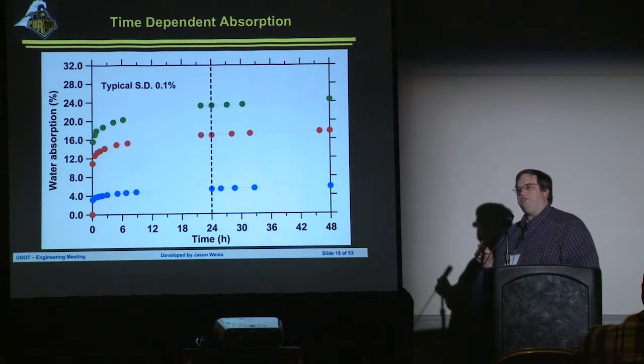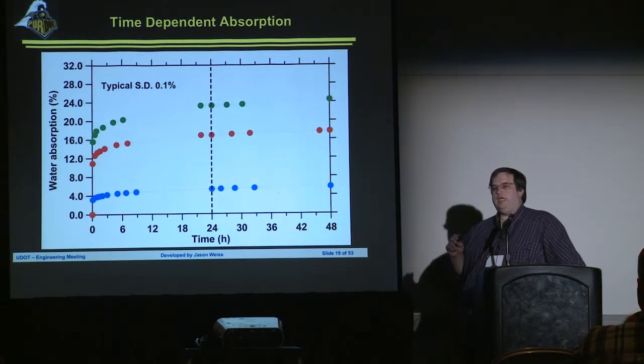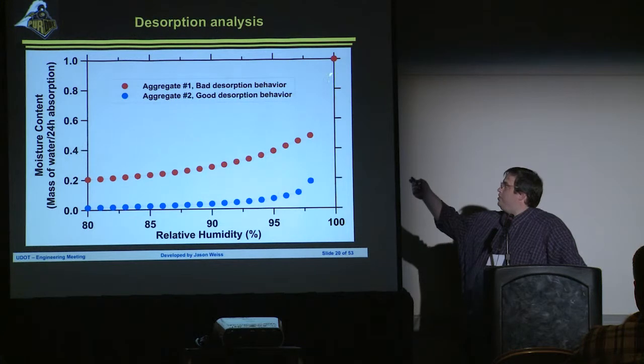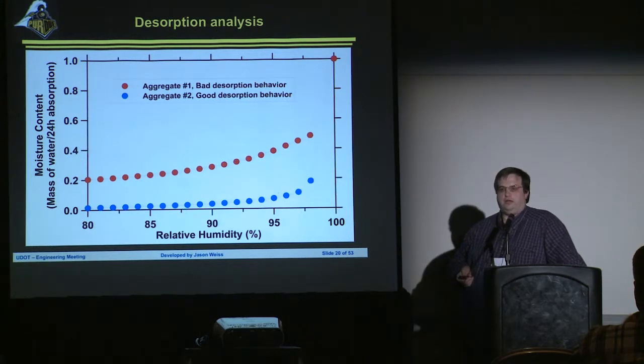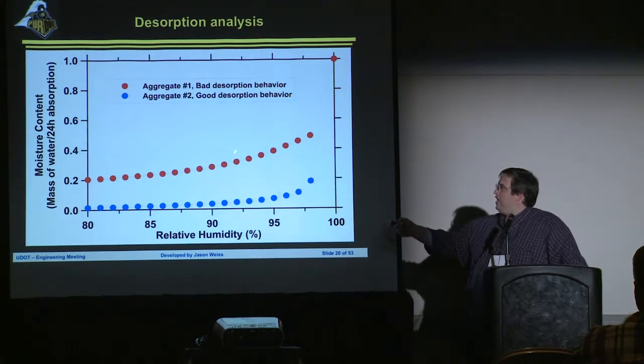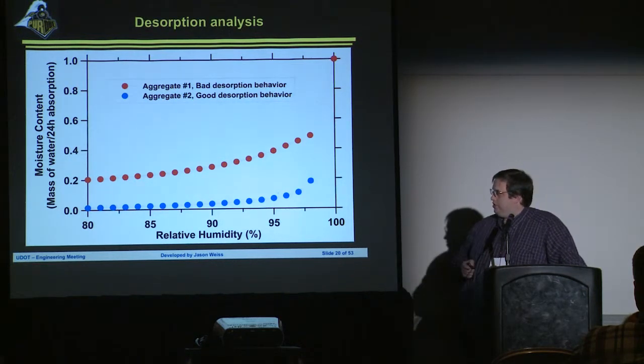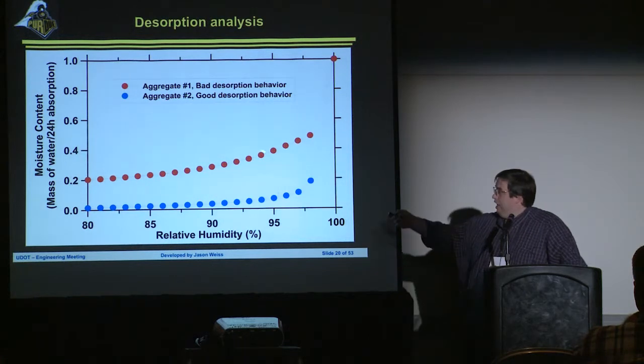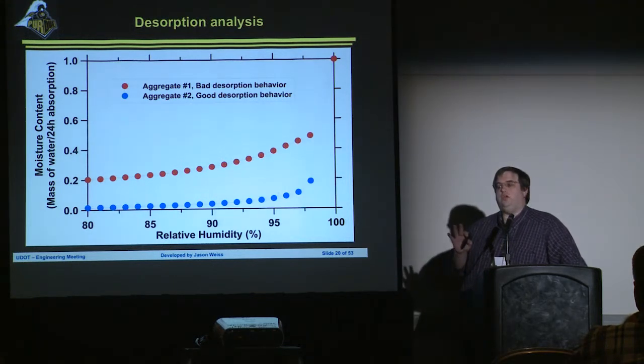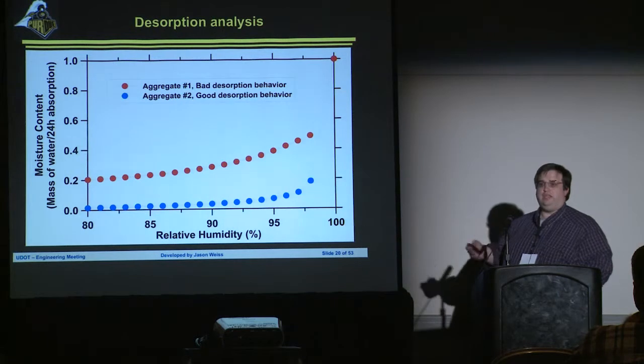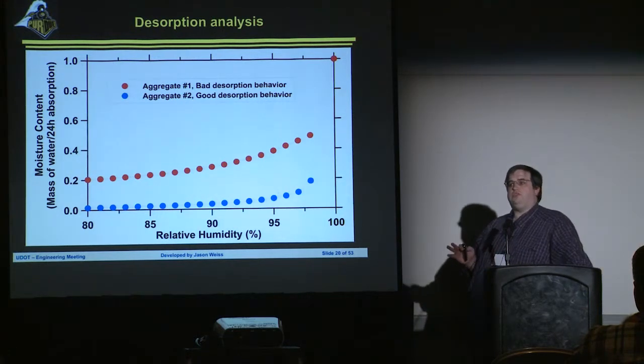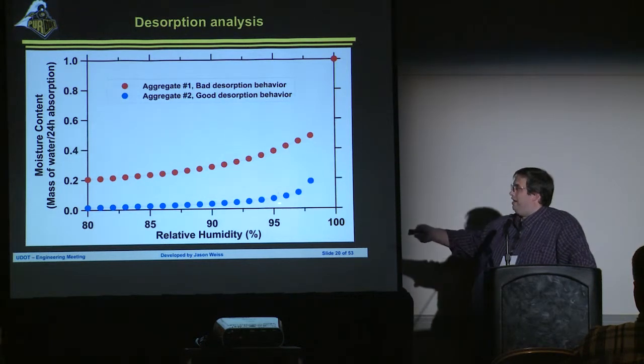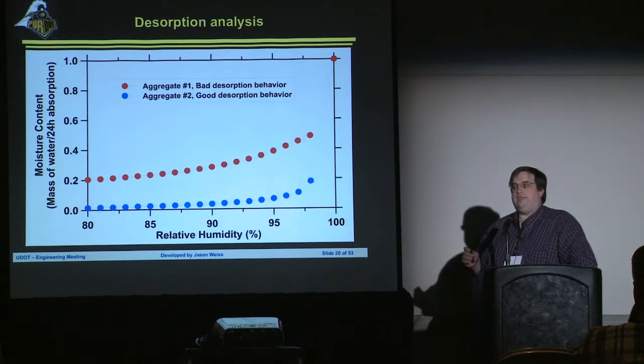But really the key issue is not necessarily water absorption. It's how easy is that water released back to the system. And in addition to measuring absorption, we've actually measured the desorption of the different aggregates. And what I would point out here again, this happens to be an aggregate that is not a shale, slate, or clay. This is a non-lightweight aggregate, but here's its desorption behavior. What we want is we want to know how much of this aggregate moisture can be lost at relative high humidities, 95, 96%. The thing that's very interesting about this is your lightweight aggregates will drop about 90 to 95% of their water at these high humidities.